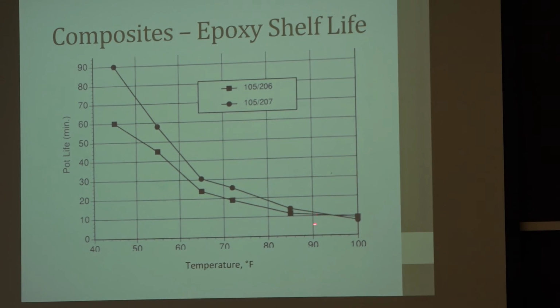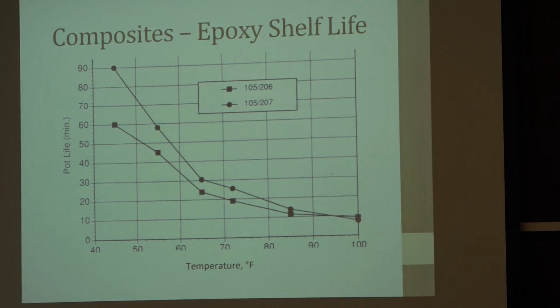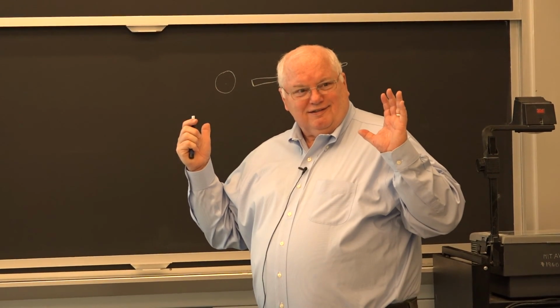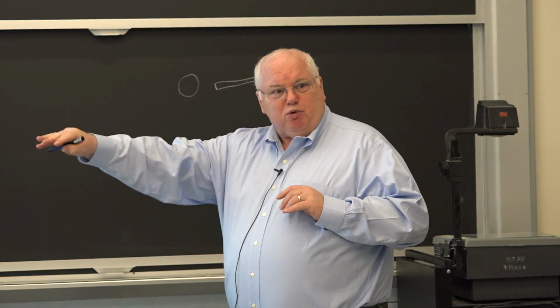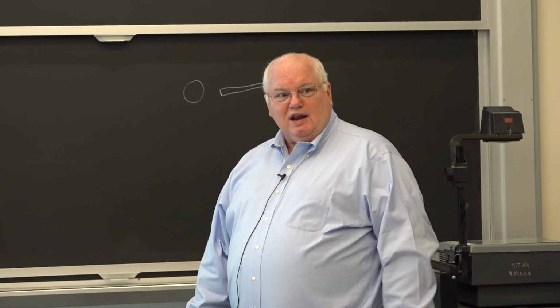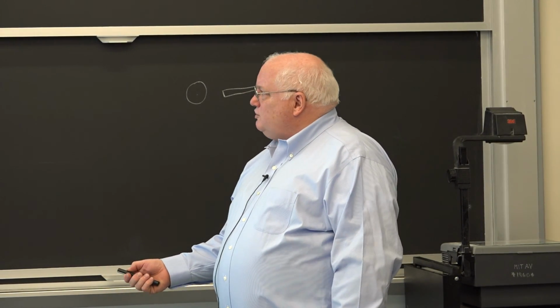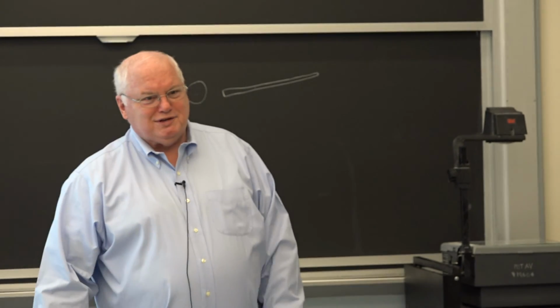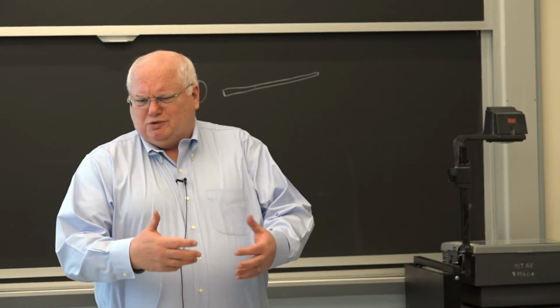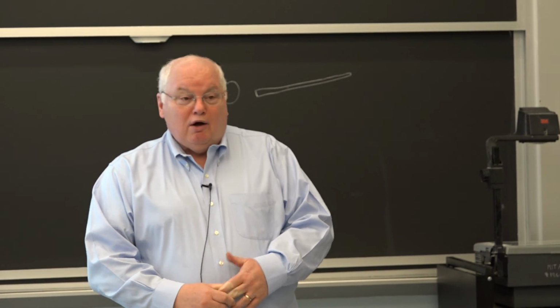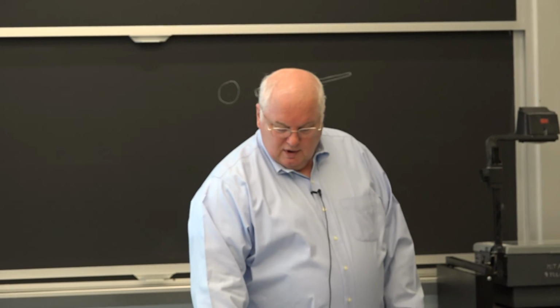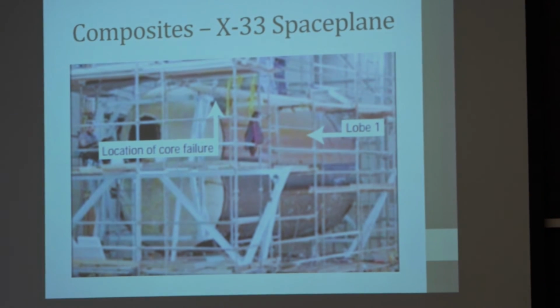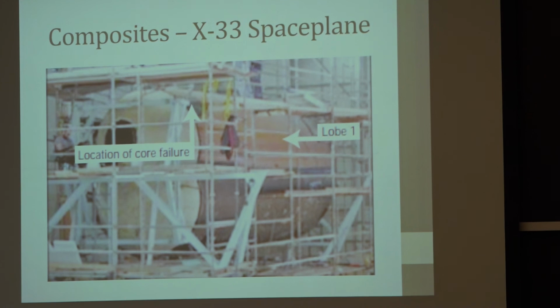Well, when 3M had their bullet point, they were talking about it having 10% of the remaining strength after 10 days. NASA had assumed that they meant it had 80 or 90% of its strength, because it said right there on the bullet point that it had a shelf life of 10 days. But 3M defined the shelf life, as good marketing people, as 10% of the expected strength. And NASA assumed, well, that must mean it has most of its strength left, right? Well, they found out it didn't have the strength. It delaminated. And they said, okay, well, it still should be good. After we do measurements on the other 2 cores that had failed, we calculate from statistics a safety factor of 1.05.